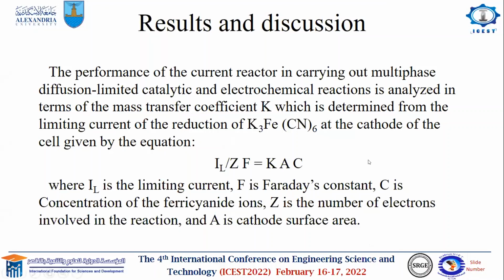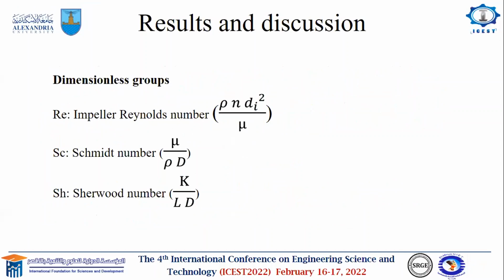IL is the limiting current, Z is the number of electrons involved in the reaction, C is the concentration of ferricyanide ion, A is the surface area of the cathode, and finally K is the mass transfer coefficient. Mass transfer correlations are obtained using some dimensionless groups as follows: Reynolds, Schmidt, and Sherwood, where rho is the density of the solution, N is the RPM of the impeller, and Di is the impeller diameter, and mu is the viscosity of the solution, D is the diffusivity of the solution, and L is the length of the cathode.